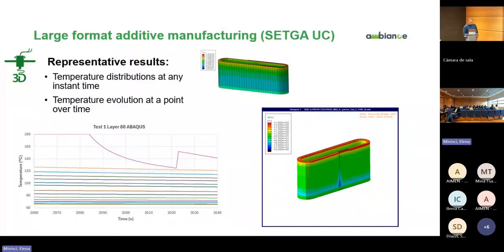We can see here one graph that is quite representative. So the material is deposited in this point at the extrusion temperature, and then it's cooling because it's transferring heat to the ambient by convection, by conduction through the material, till the next layer appears. When the next layer appears, it jumps again. So we are interested in this minimum point because it will determine the quality of the adhesion.